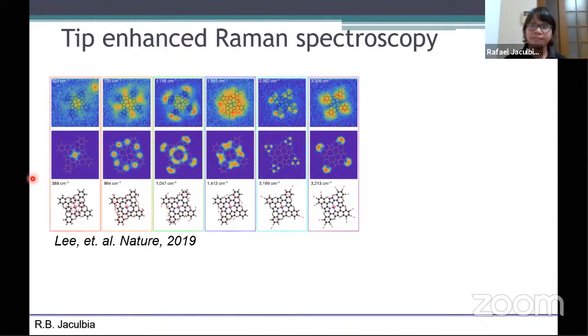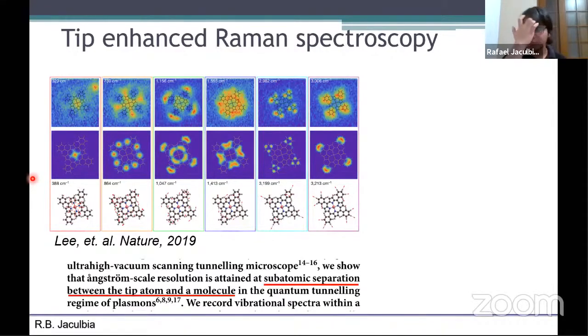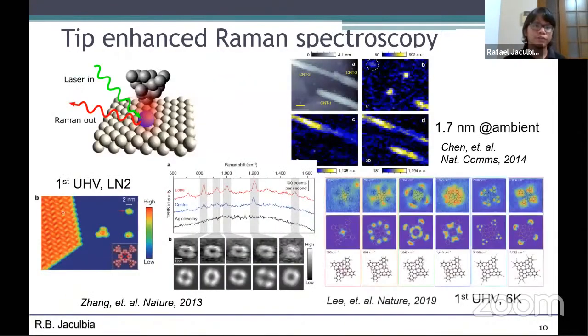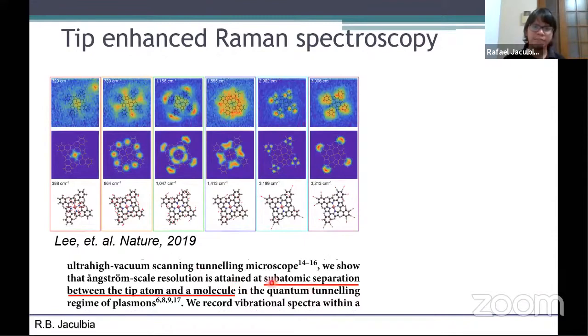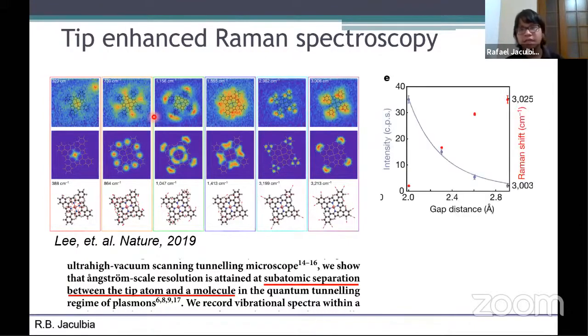So you can detect the difference in signal within the angstrom scale. However, in order to achieve this, they had to approach the tip. So as I mentioned before, you have to put the tip. And in this work, in order to achieve that great spatial resolution, they had to approach the tip to the molecule. And in fact, they themselves said within subatomic separation. So the distance between the molecule and the tip is very near.